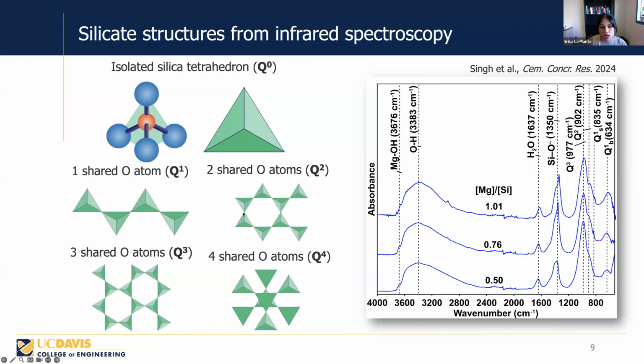Q2 would be two of those oxygen atoms shared, forming double chains. Q3 would be three oxygen atoms sharing, forming a sheet. And then Q4 would be a framework, so all of the oxygen atoms are shared. So here on the right is characteristic FTIR, Fourier transform infrared spectroscopy data, showing the absorbance as a function of wave number, and also showing the different peaks that we have observed and how we've indexed them to the different silicate species.